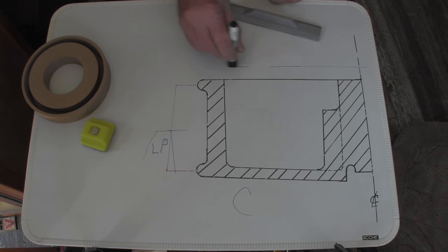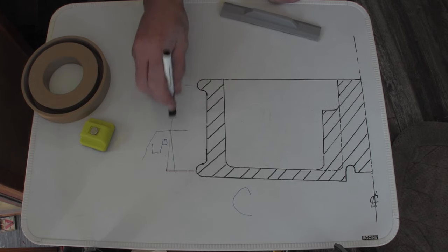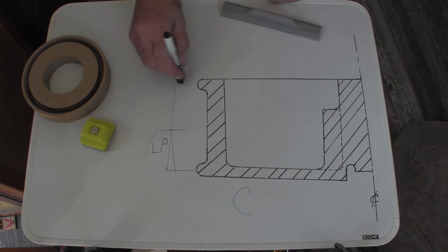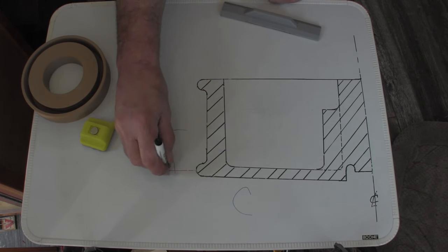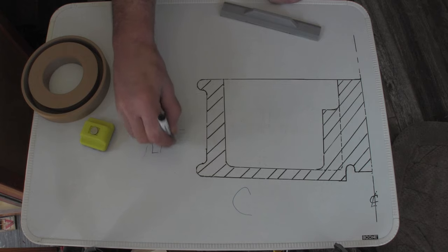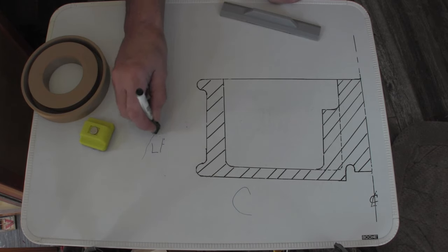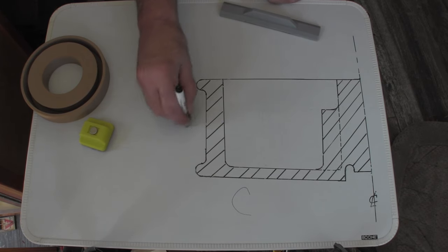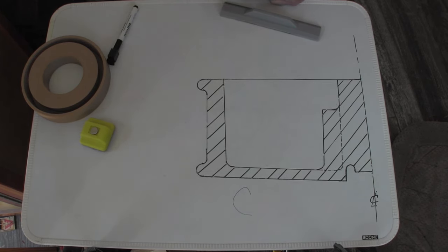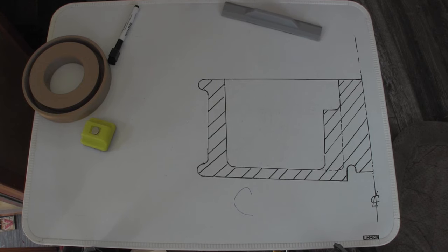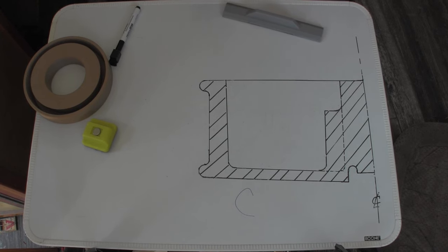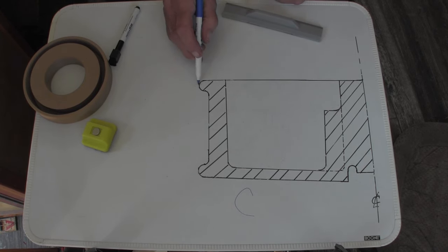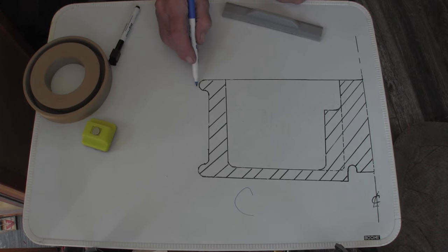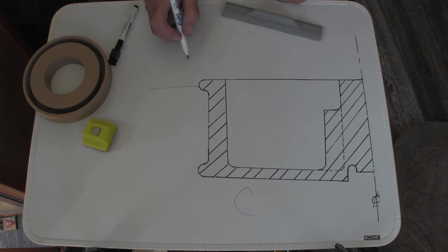And it's still the drag, but get rid of this core. You don't want this core at all. Is there a way that you could make this pattern by not using any cores? Yes, there is. And that is you use a cheek. And what Clark did is, if you want to use a cheek, come out this way. That would be the parting line. This is a drag.